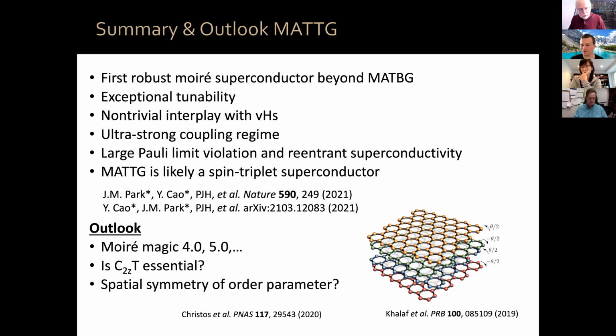said, we have a few thousand atoms in the system, maybe a few 100,000 atoms. We do not know if the technique has that sensitivity, probably not. Now, there are other ways to measure spin susceptibility, and in particular magnetization of the normal state, to see what happens in the normal state, and to see if the system is spin polarized or something like that. We are planning experiments to carry out those measurements. We have done such measurements with magic angle bilayer graphene. We haven't done them yet with the trilayer, but we hope that those measurements will give us some information.